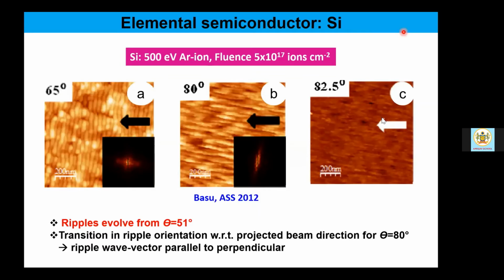Now I'll start showing you a lot of examples. As I told you, this is the first case where, depending on the variation of this incident angle, we get to see various patterns on silicon surface. For instance, at an incident angle of 65 degree, we get to see these ripple patterns. Then at 80 degree, we also get to see rotated ripple patterns, needle-like structures. And at 82.5 degree incident angle, we get to see a nearly flat surface.